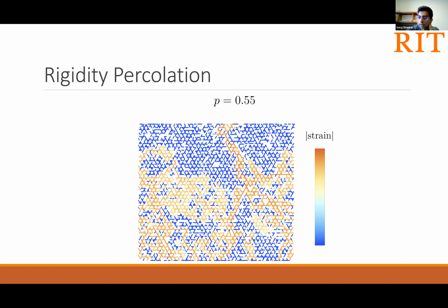And can I ask a question? If I understood the experimental data that you showed first, that was measuring shear response in the presence of compressive load. Is that correct? Yes. So, when we stand on our joints, of course, we're putting them under a little bit of compression. And so yes, the experimental apparatus mimics that by applying a slight compression to the samples, and we've mimicked that in our simulation protocol.